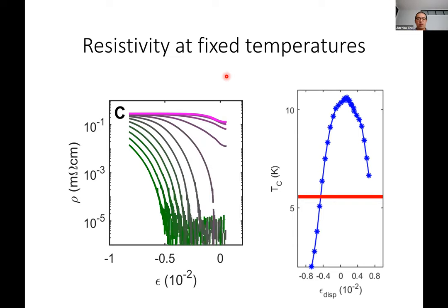Now, as a side note, we are also doing resistance versus strain measurements. You can see that simultaneously, while you're driving the system out of the Meissner state, the resistance also increases from the noise floor all the way to the normal state value. There's a huge modulation of resistance, about 4 orders of magnitude of change as you apply strain.